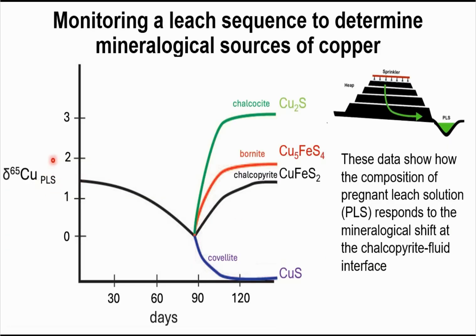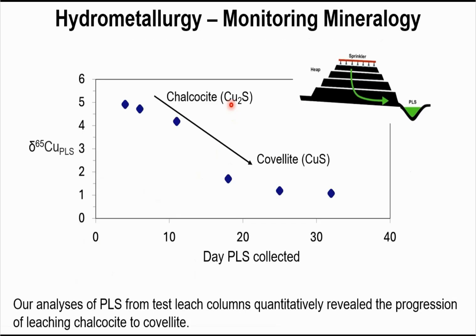So we started analyzing that pregnant leach solution. And what I'm showing here is that for a given heap leach operation, if we sample the pregnant leach solution at any time after leaching has begun, we can measure and use, as the y-axis indicates, the copper isotope composition of the pregnant leach solution to tell the mining company what copper minerals are being leached at that point in time. This is important because it allows the companies to modify the composition of the lixiviant that they spray on the top so that they can control pH, which is a huge factor in determining reactivity of the lixiviant with copper minerals.